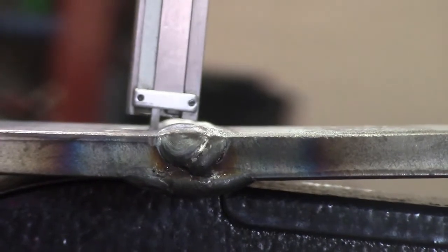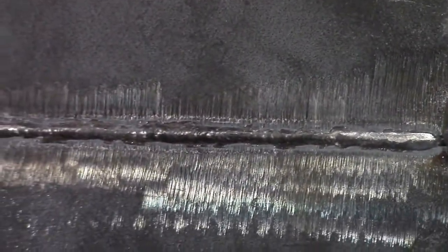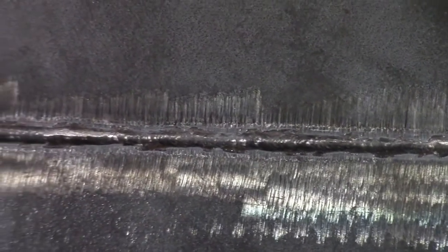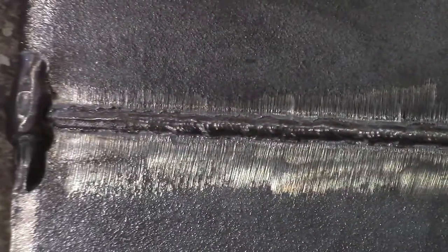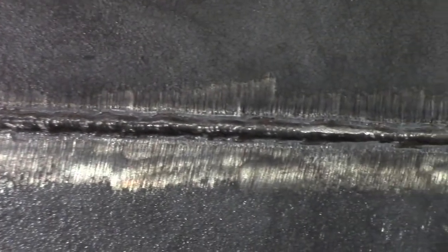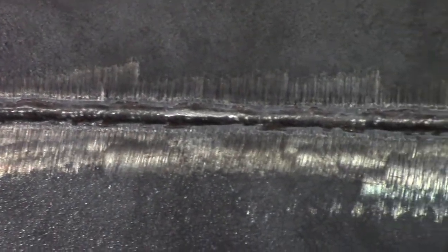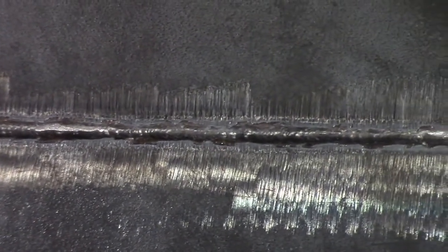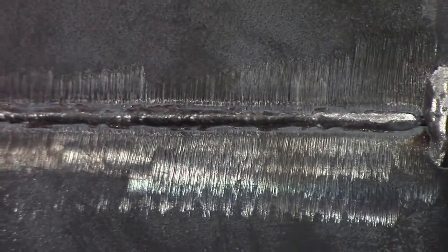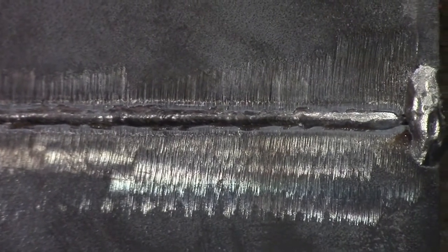Now we're going to take a look at the root. All right, here's our root pass. You can see it's got penetration the whole way down the weld, so we're going to try and zoom in on this again like we did with the face. It's pretty uniform all the way down. There's no lack of penetration, there's no holes or nothing, no lack of fill, there's no suck back of more than 1/32. So we're going to be good to go to our bends here, but we'll check the convexity first.